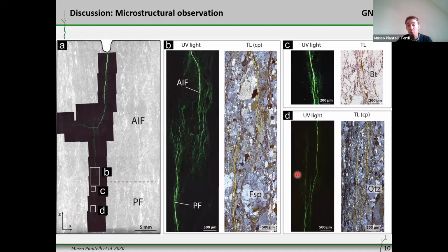And we could see and prove that the fracture went really through the weaknesses inside of our rock sample. So preferentially the cleavage of preferentially oriented biotite grains, for example, ultrafine polymineralic aggregates, it ran through those very easily, and alongside grain boundaries, for example. And we related the propagation of this fracture to fast events. Because the fracture really runs very quickly and easily in there, it doesn't really need a lot of strength